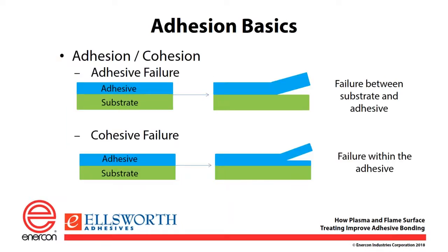When talking about adhesion, and in particular if you're talking about the failure of an adhesive, it's important to recognize the difference between adhesive failure and cohesive failure. Adhesive failure is the failure between the adhesive and the substrate that the adhesive is bonded to, whereas cohesive failure is actually failure within the adhesive itself, where the adhesive breaks apart. In the case of cohesive failure, it means that your bond strength between your substrate and your adhesive was actually greater than the bond strength of the adhesive to itself. That's generally the preferred method of failure. If you're going to see failure, you want to see it cohesively, but this assumes that you've selected an adhesive that's got a strong enough bond in the first place to the substrate that you're working with.